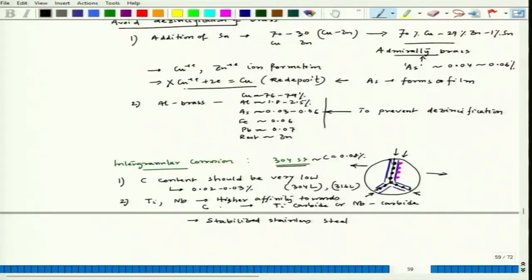If we have excessive potential difference between the grain boundary and grain body — due to dealloying along the grain boundary or precipitation along it — that leads to intergranular corrosion. For example, if chromium carbide forms, the chromium carbide is noble compared to the surrounding chromium-depleted zone where chromium can drop below 12%. That narrow depleted region acts as the anode and the chromium carbide region acts as the cathode, creating galvanic current and strong dissolution along the chromium-depleted zone. Similarly, in copper-based alloy systems, anodic precipitates along grain boundaries can dissolve, causing intergranular attack.